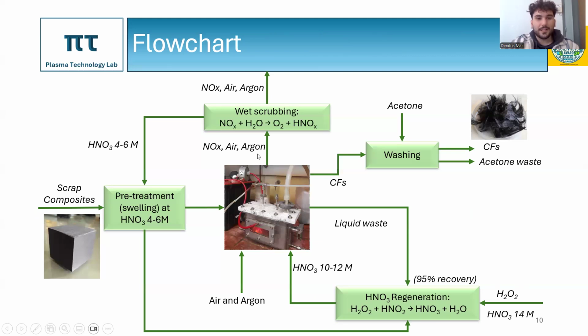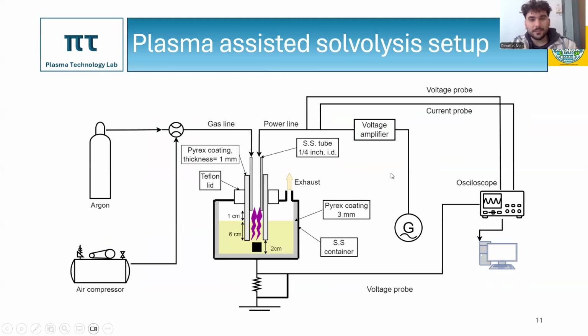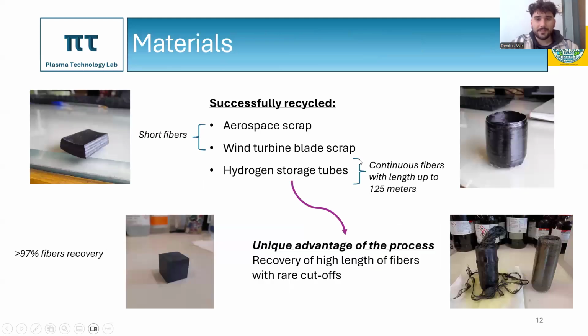The heart of this flowchart is the plasma-assisted solvolysis, which has a setup of its own, right here. Basically, inside the stainless steel reactor, which is coated with glass, the scrap composites and the nitric acid are placed. Also, inside this reactor, there is a cylindrical electrode, which allows the gas flow in the form of bubbles. This electrode is powered by a 30 kHz generator, and this is how plasma in bubbles is generated inside the solution.